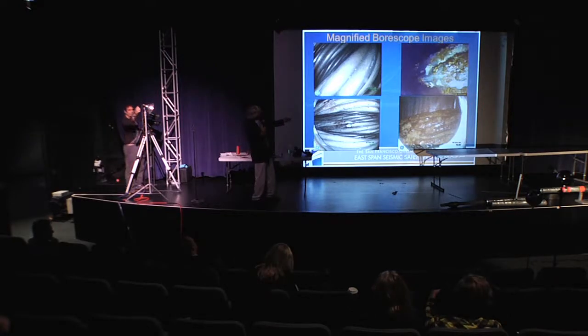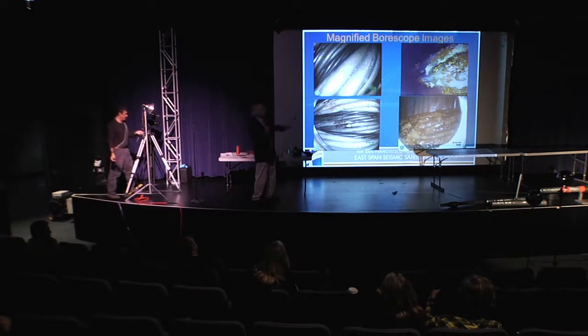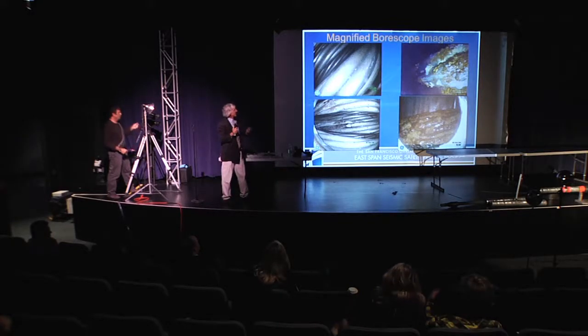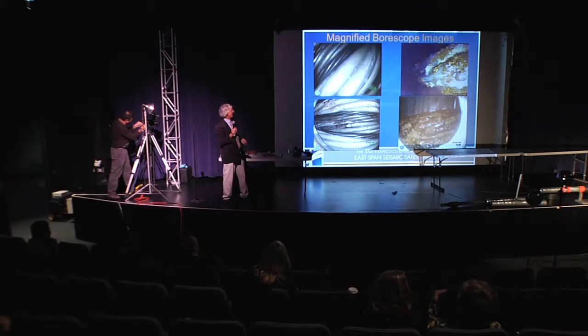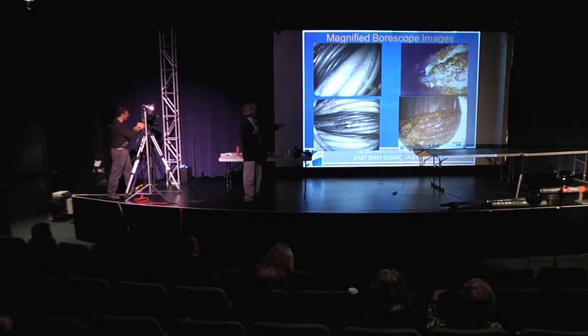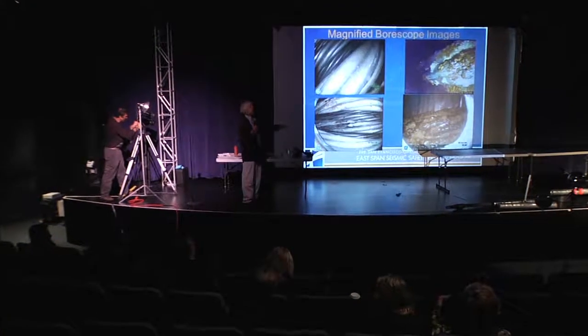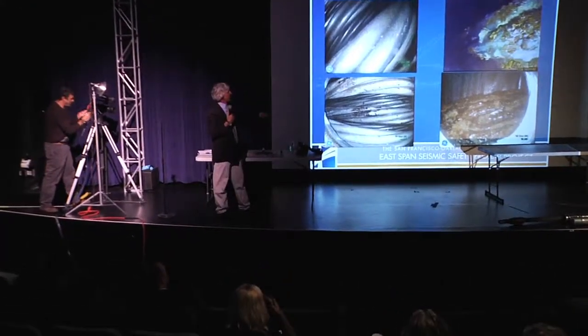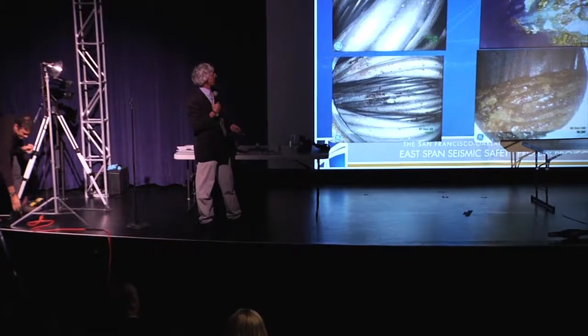And when you see the steel, it's very, very smooth, and then you see clearly surfaces of the steel, and you see some of this. It's really not the steel oxidizing. It's really the chemical reaction between the moisture and the actual protective powders that we put in. And then down below in the bottom right, you actually see some of the worst stuff that we saw. This is what was termed moderate corrosion.